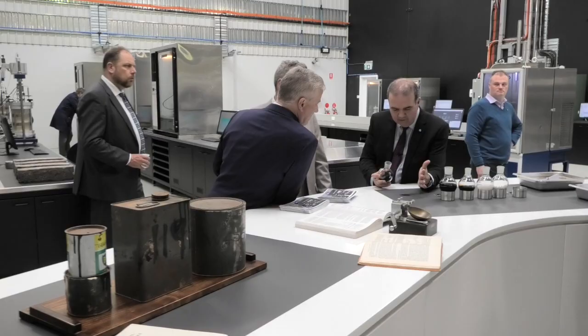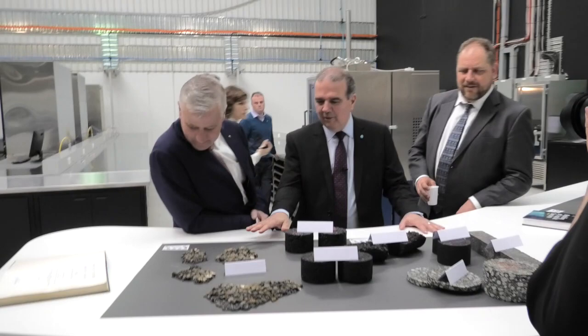Technologies like sulfur-reduced concrete — as used at Toowoomba's Wellcamp Airport — are tested here. Crumb tyre rubber incorporated into bitumens and asphalt: 20% by mass can deliver 50% thinner pavement with the same quality of life — quite remarkable. These styrene-butadiene styrene particles go into asphalts to make them very stretchy, along with elastomer pellets. The next generation of technology for us is taking the waste stream from plastics, getting them into a usable form, and adding them with bitumen — it's a pretty high-viscosity product.